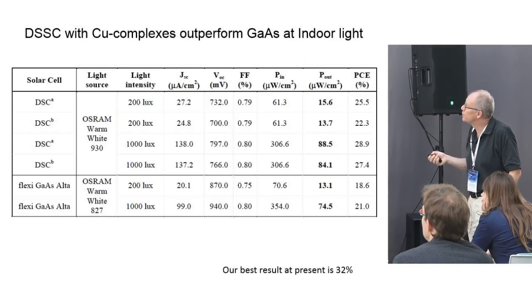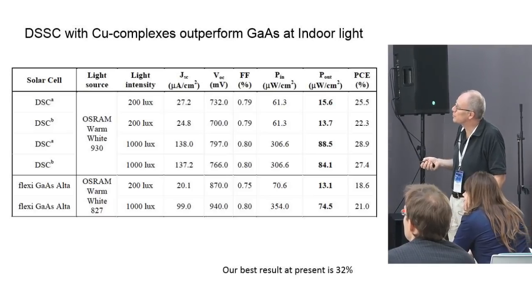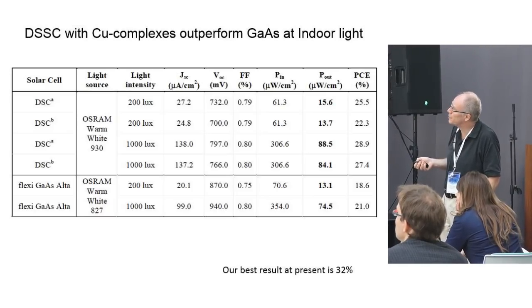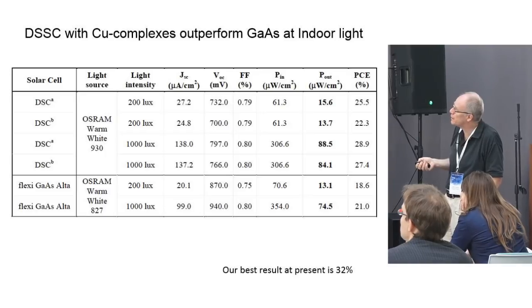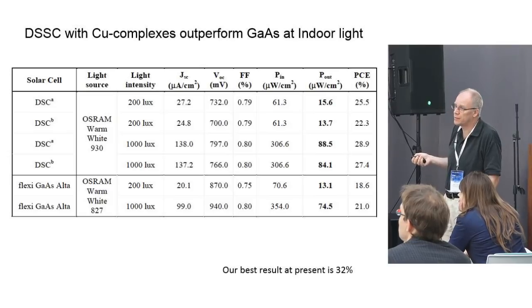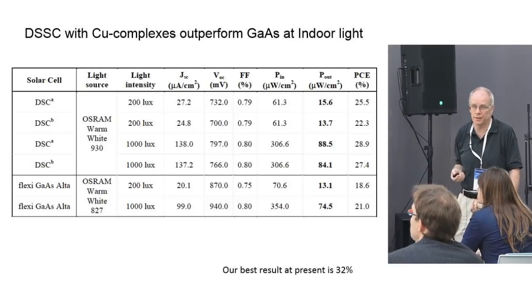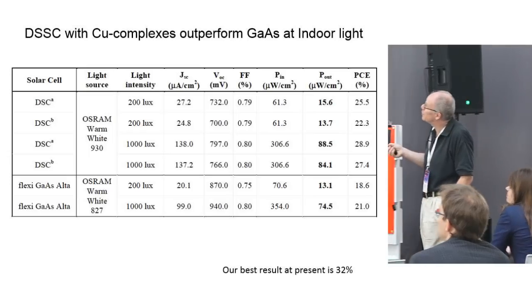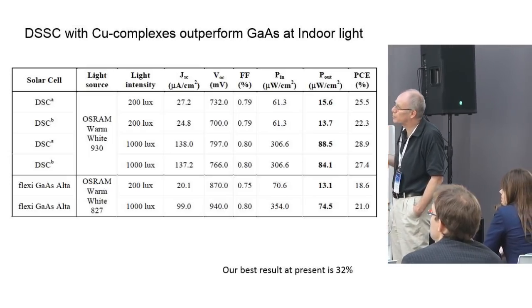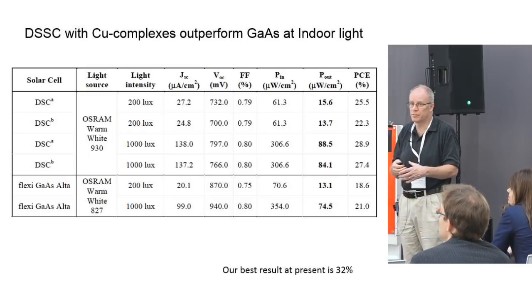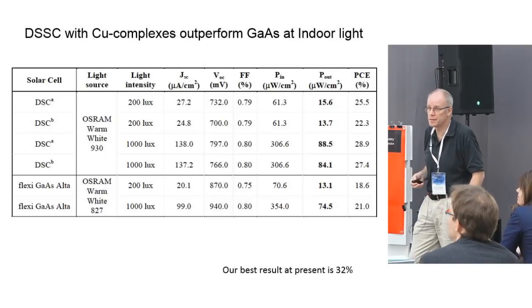And you see here we compare this value with the best solar cell there is, and that's gallium arsenide, which has the world record of 29%. They are very expensive, but the best solar cell, and we are dye-sensitized, are even better than the gallium arsenide for indoor light, much better than silicon. And so here we think we have maybe the best technology for using solar cell for indoor applications.